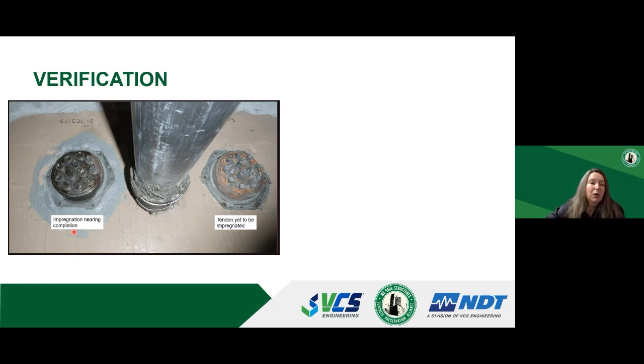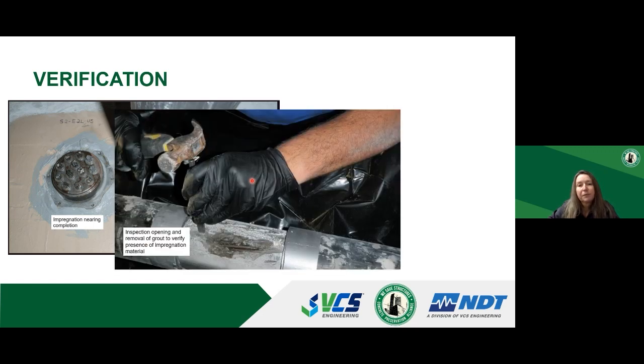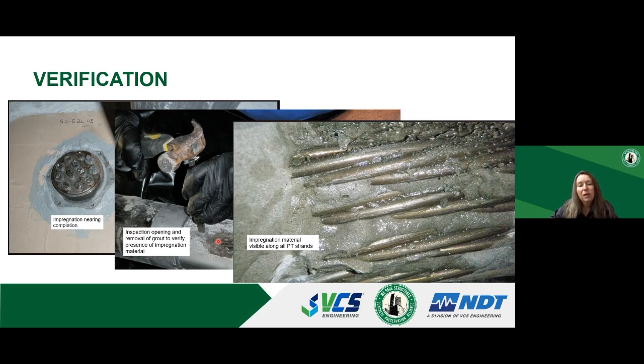Again, you have the darker anchorage on the left, that's coated in the impregnation material, and on the right for comparison is the anchorage that has not been treated yet. Here's another verification opening. Again, you see the darker color of the grout, which confirms that the anti-corrosion material got to that point. And here's an up-close view that shows the higher sheen of the strands from the coating.